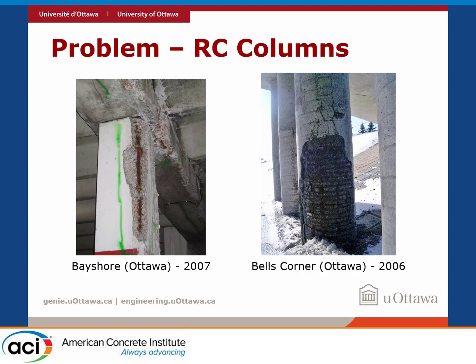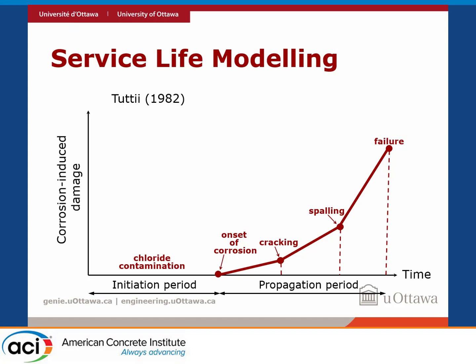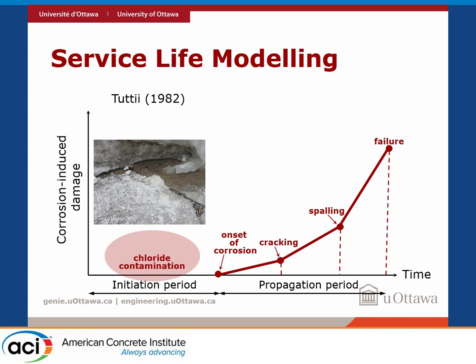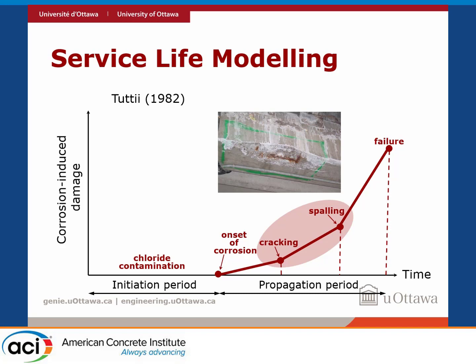Now, in general, the process of corrosion of steel in concrete is idealized as a two-stage process following an idealized model by Tuutti, who was a pioneer in the studies of reinforcement corrosion in concrete in the early 80s. It idealizes an initiation stage where either chlorides penetrate the concrete cover or carbonation of the concrete happens, and then the onset of corrosion occurs. This is a period that has been quite a bit researched, and there is a lot of literature studying the process of either carbonation or chloride diffusion into concrete. And once corrosion starts, there is the ensuing cracking and spalling or delamination, depending on the stage of damage.